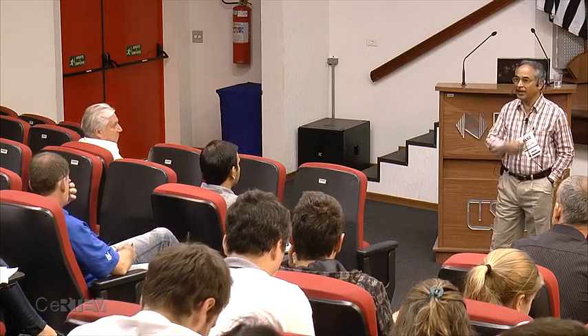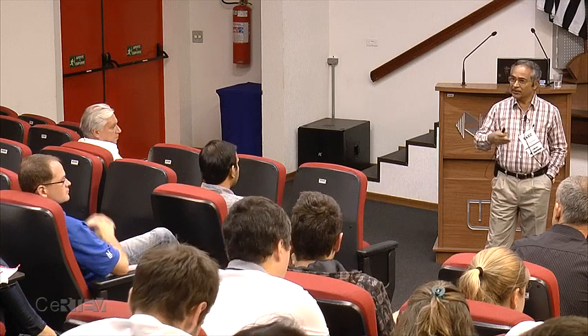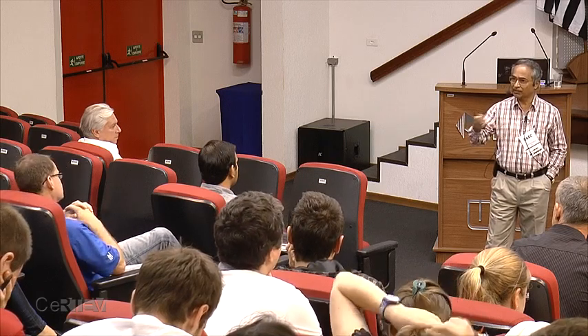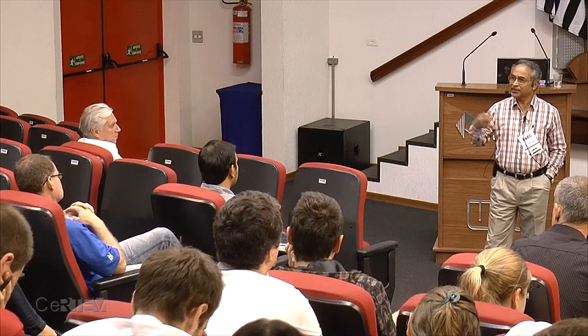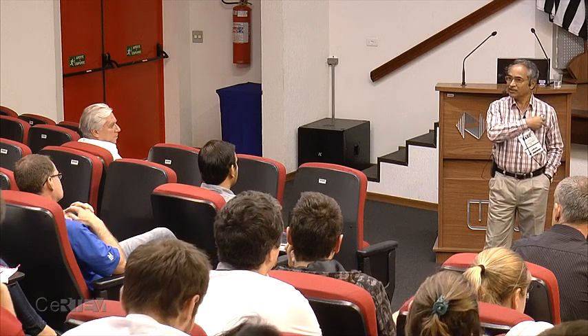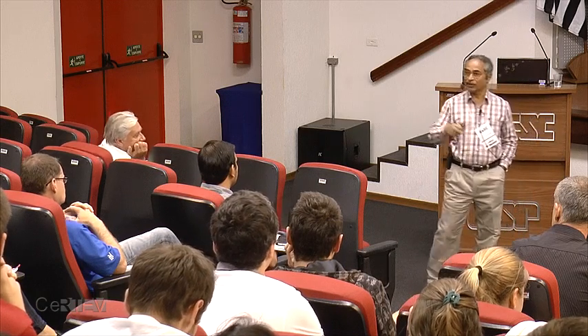Which one is comparable? In such glasses, I have measured XPS, which I have not shown here, and calculated the density of bismuth 3+ and 5+. I have shown it is mostly 3+. So if there is a slight existence of bismuth 5+, so that electrons can hop, we have a very small conductivity compared to the ionic conductivity. So in our system, there is no role of electronic conductivity. We have checked, but you have to check by XPS, particularly if the content of bismuth is high.